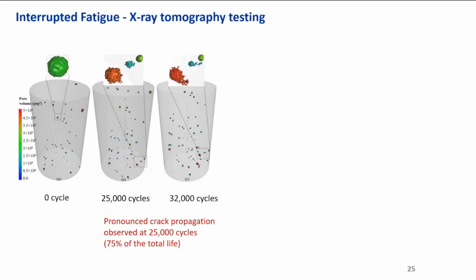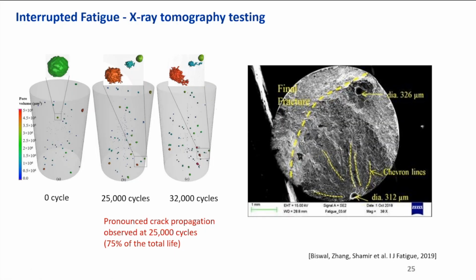We also did a tomography we call interrupted tomography. After every 5,000 cycles, we stop fatigue testing and do X-ray tomography, and we found pronounced crack propagation from the pore around 75% of the total life. Obviously, this depends on the stress levels applied. What I really want to say from this fractography picture is there is always one killer pore. It's not depending on how many you have, and it's also the location of that pore. These big ones in the bulk of the material are almost like hibernating there, but the one very near to the surface is critical because the stress concentration is high. There's no material on the other side to carry the stress.